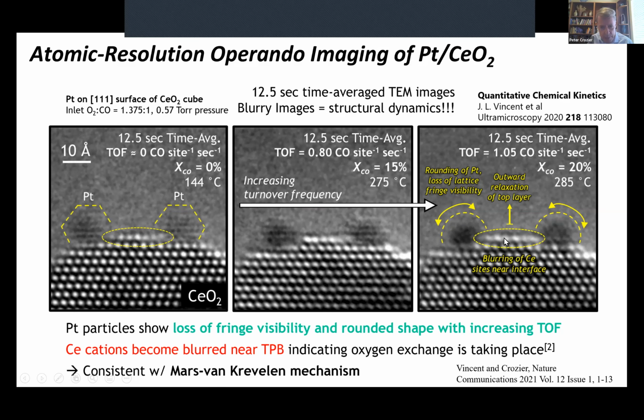And of course, you see immediately this blurring of the surface atoms of the ceria, which we now know is associated with oxygen vacancy creation and annihilation. And you also will see now blurring of the platinum nanoparticles here. You can see that in these images on the right-hand side, it's hard to see the lattice fringes, and that's because these particles are undergoing the kind of dynamic fluctuation that I showed you before.